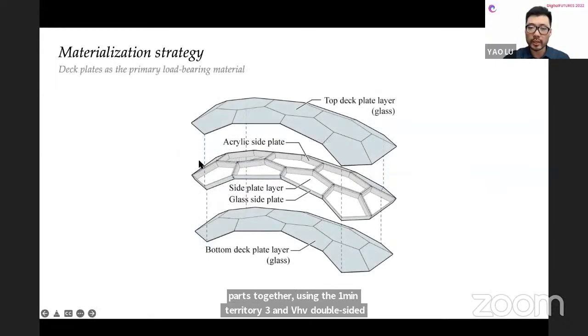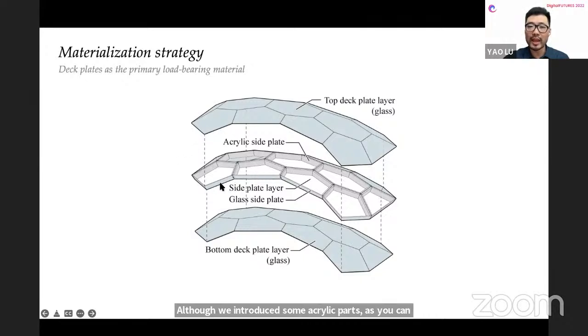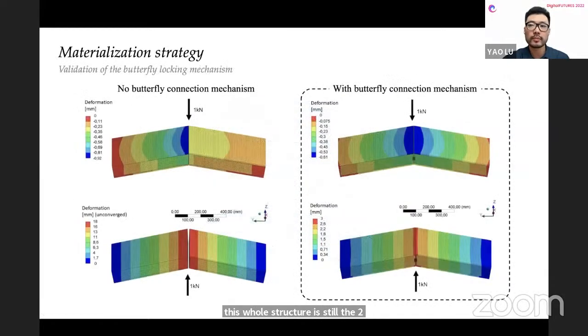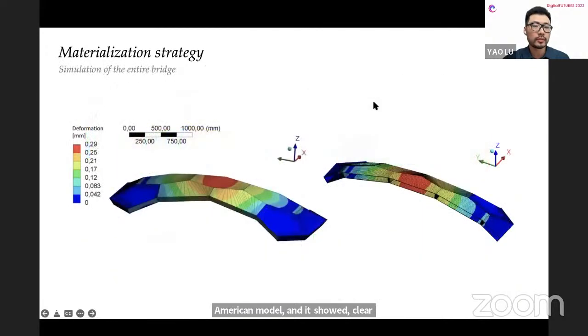Although we introduced some acrylic parts, as you can see in this middle layer, the primary loading elements of this whole structure is still the 2 continuous layers of the deck plates. Then we validated this improved connection mechanism using a simplified numerical model, and it showed clear improvements. The entire structure was also simulated under its self-weight, and the maximum deformation is below 0.3 millimeter.